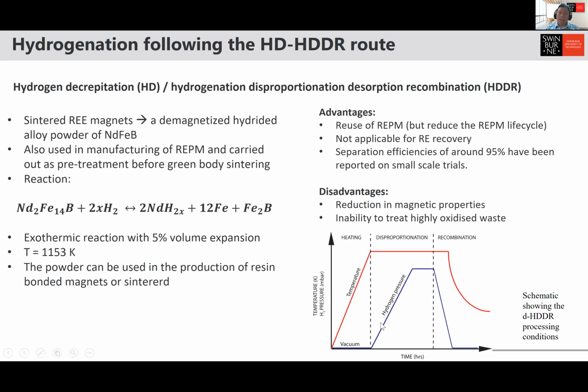Yeah. So the one on the bottom there is the process conditions that we use for this process. In essence, first we put it under vacuum and then we heat it up to a particular point. So usually it's 1153 Kelvin, quite a high temperature. And then we bleed that with hydrogen. So you use hydrogen pressure in there. And as you introduce the hydrogen into the reactor, then the reactions happen. So this is disproportionation reactions and formation of hydride. And then of course, you do recombination by lowering the pressure as well, and also the temperature.